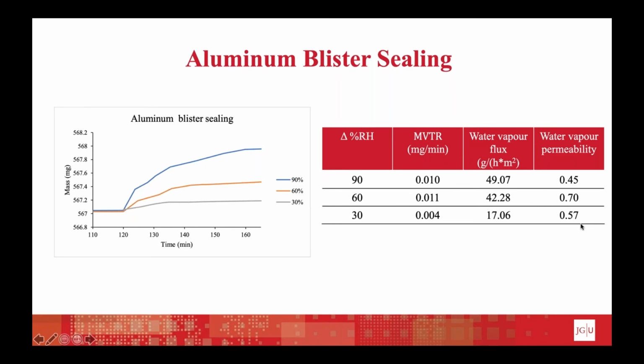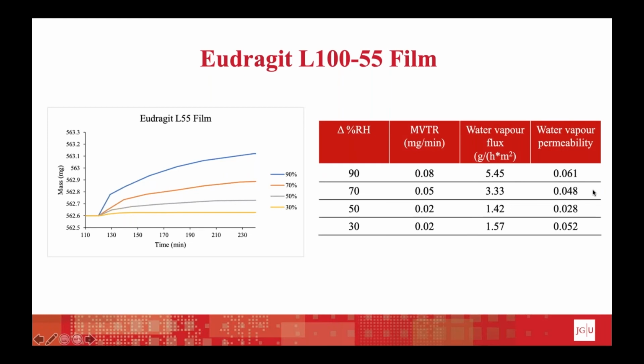We also investigated the permeability on aluminum blister sealings, which is typically used in pharmaceutics. And what we see here is that we have a much lower flux of the water vapor, resulting also in a lower water vapor permeability, being around 10 times less than in the paper bag situation. Last, we also applied this method to a Eudragit L100-55 film. So this Eudragit is again a coating material. So if we have a casted film, we can also test a coating formulation in this experiment. And what we saw here is that the water vapor permeability is even lower than in the aluminum sealing seen right before.